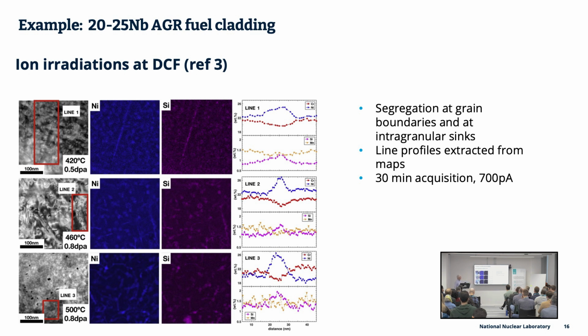And the choice there, I guess, is that if you want accurate quantification of what's at the grain boundary, then maybe mapping isn't the thing, or maybe you need to map over a much reduced area, something to get more counts into those spectra. You can produce what looks like a really plausible map, and then you extract the individual spectrum that underlies each of those points, and you'll find there's only a remarkably small number of counts in it, and certainly nothing that would bear any form of statistical analysis.